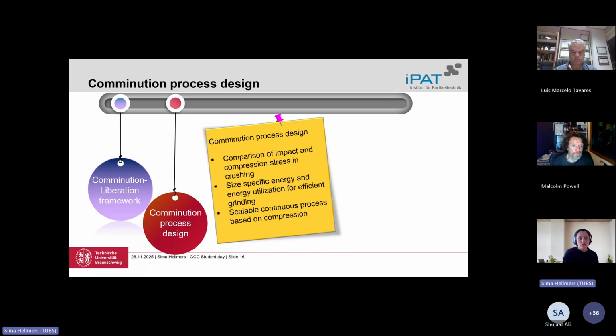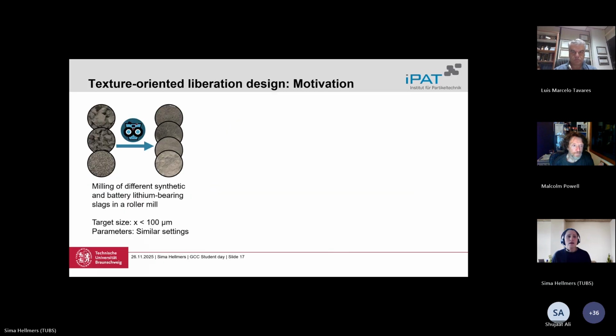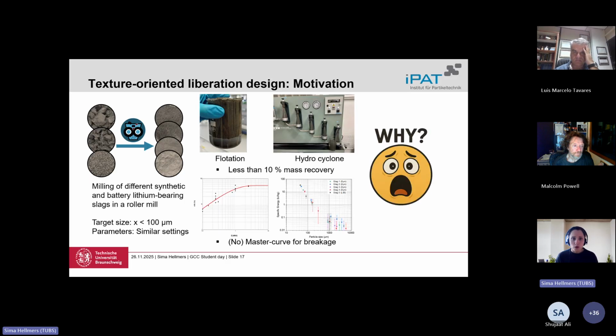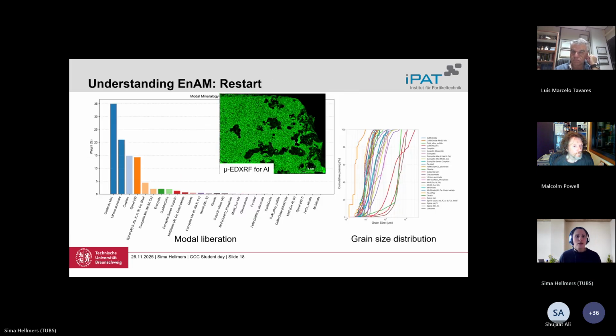That was the positive part of the flotation, but we used different slags, and then there was something that went wrong. Like we had a flotation for some slags that didn't work at all, or we tried to use a master curve for the breakage, but it didn't work. So the question was, what happened? What was wrong? Let's look at it differently. So we used mineral liberation analysis to look at the slag again and see what happens on the surface of the particle. Are we just reducing our particle size, or does something happen on the surface?